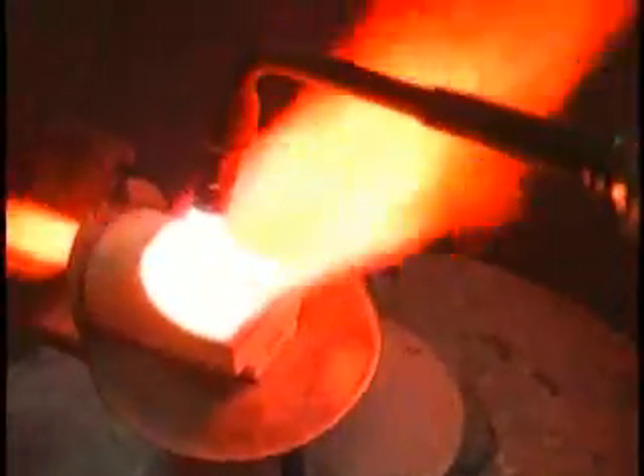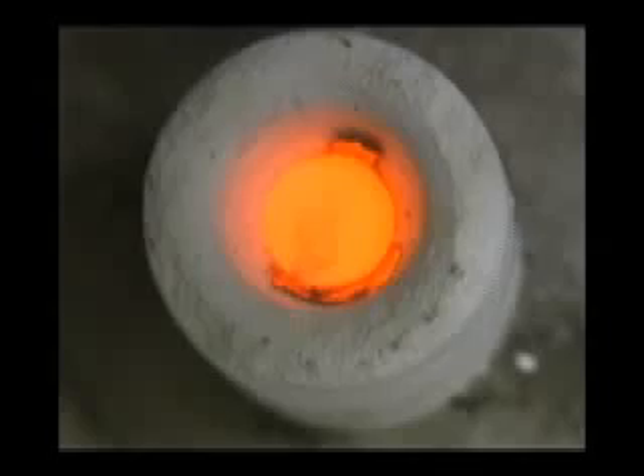The typical crown contains a palladium silver tin alloy with small amounts of iridium and zinc. Once the metal has completely melted, the investment casting is removed from the furnace and placed behind the opening in the crucible inside the casting machine. The pin holding the machine is released and the centrifugal force pulls the molten metal into the mold cavity. The investment casting is removed from the machine and allowed 2 hours to cool.